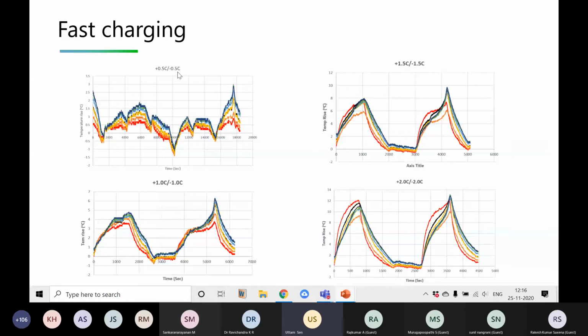Okay, so in the case of 0.5 C charge and discharge, we can see that the maximum temperature rise from room temperature is up to 3 degrees. Okay, so let's say the temperature of the room is 25 degrees, then the cell temperature could hit up to 28 degrees. When we go to 1 C, the maximum rise is 6 degrees. When it is 1.5 C, the maximum rise is 10 degrees, and at 2 C, the maximum rise is 12 to 13 degrees.